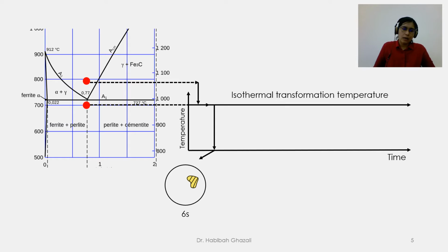So now, if they look under the microscope, what they can see is that some fraction of the microstructure has been transformed into pearlite for this temperature, 700 degrees. Some has been transformed into pearlite, the rest still retains the austenite. So this doesn't really matter. They just want to see how much fraction has been transformed from austenite to the different microstructure or different phase.